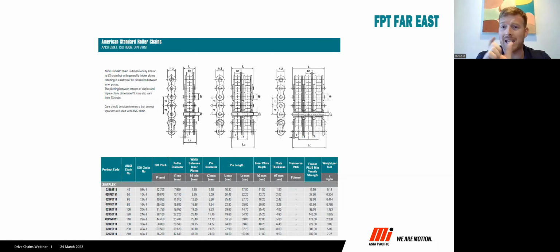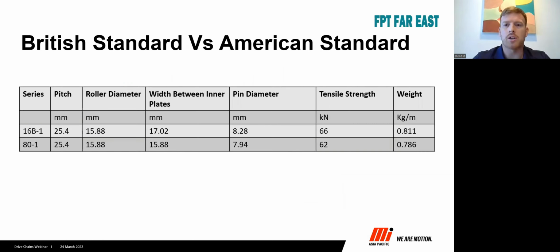There are chains that are made with metric pitches, but those are less common in the industry globally. So here's just a comparison between a 16B chain, very common in industry, and an 80-1 chain. 16B is the British standard, 80 is American standard, and the pitch is the same. The roller diameter is the same, but the width between inner plates is different, and the pin is a different diameter. And you can then see the tensile strength between the 16B and the 80 is different, and that impacts the weight of the chain.